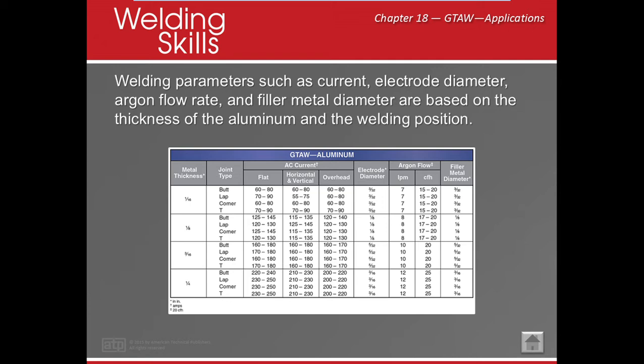Okay, so what happens when we don't clean it right? Well, the weld just doesn't come out when you weld it. It almost seems like it's gummy or the bubble is just stuck under there and it doesn't break through. It has some sort of covering. Well, that covering, that's oxide. Okay, so another issue if you don't take that oxide out is oxide inclusions. Since those oxides are also heavier than the aluminum, they can sink to the bottom of your weld and create oxide inclusion. So pretty important, right? Cleanliness is important regardless of the material you're using, okay?